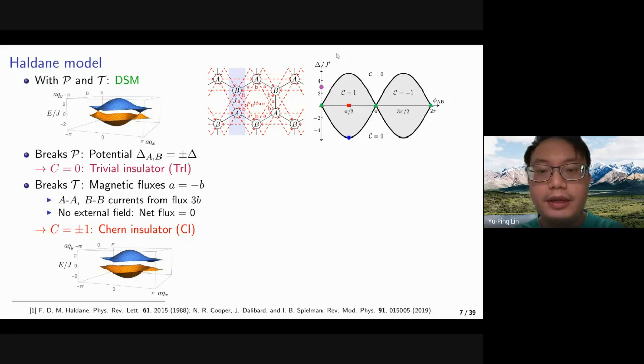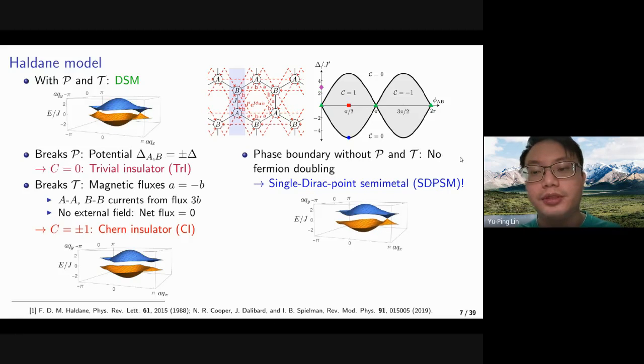However, if we look broader in the whole phase diagram, we generally don't have either inversion or time reversal symmetry. And there are some continuous phase boundaries which are not Dirac semimetals. So what are they? First, we can think carefully: if we don't have inversion or time reversal symmetry, the energies, the band structures at k and minus k don't have to be symmetric. So we do not have the fermion doubling theorem here.